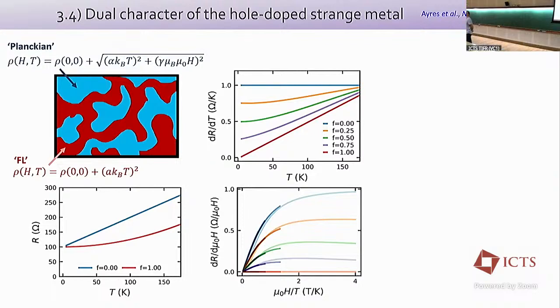So the observation of quantum oscillations in the thallium system required, let's say, an electronically homogeneous state over a region of about 500 angstroms. So that's quite a large scale. I mean, the scales we're seeing in the BISCO are 50 angstroms, if that, and similarly in LSCO.